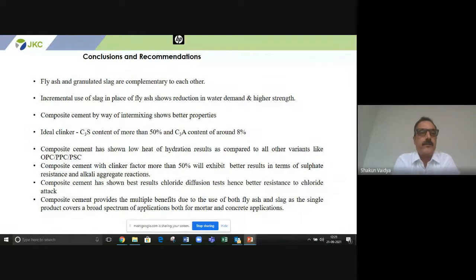They are complementary. So incremental use of slag in place of fly ash shows a reduction in water demand. So we achieve better workability at a lower water cement ratio, resulting in high strength. Composite cement, by way of intermixing, shows better properties.